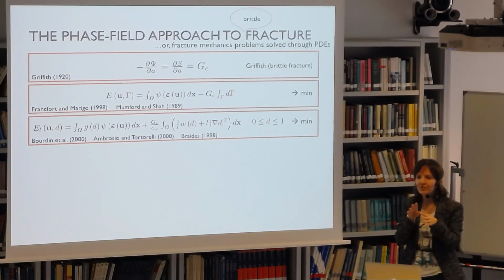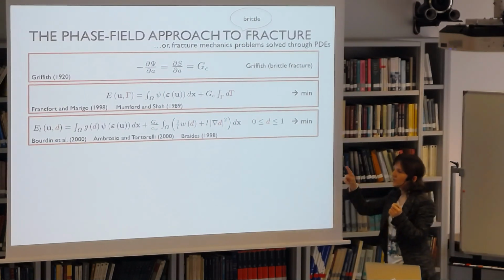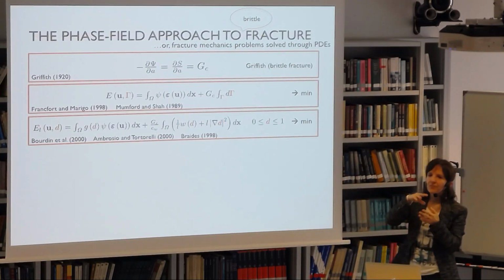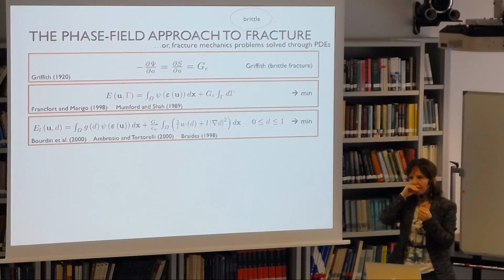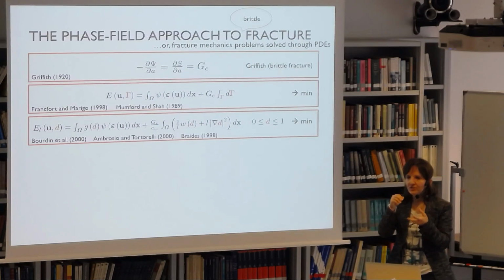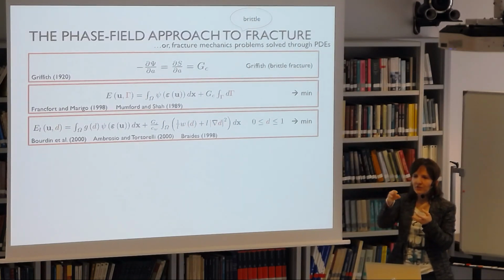It's not a real cohesive behavior in the sense that the crack faces are still stress-free. They don't have any residual stress after the crack starts. But the presence of this length scale introduces, let's say, some additional richness. It was Corrado who showed, in a PhD thesis by Jean-Jacques, that if you tailor L, you can match the tensile strength of the material.